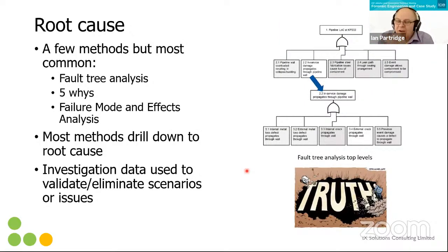Root cause. So you've done all that work, and next you do a root cause. There's quite a few methods. Personally, I prefer fault tree, where you start at the top. So in this case, a pipeline leak at a certain location, and then you look underneath at all the different potential scenarios, and you follow the branches down till you get to the very bottom, the root cause. And it may not just be one root cause, there may be a couple of root causes.